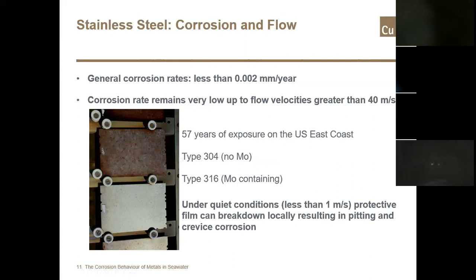It's around 0.002 millimeters per year. But this is achieved by ensuring that oxygen is available by the flow of seawater across the stainless steel surface, and this obviously helps maintain the protective film, and the material remains passive and immune from major material loss and corrosion.